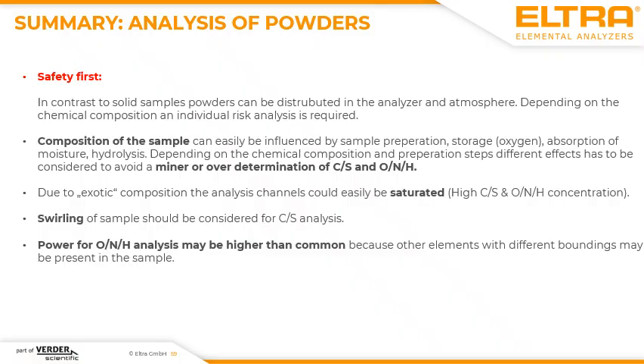And for ONH analysis, the most critical thing is the applied power. For example, when you are familiar with operating steel samples as solid samples, and now you are getting a steel powder, it could mean that you have to increase the applied power to make sure that all of the oxygen and nitrogen releases from the sample. These are the most important hints which I would like to give you when you are facing problems with analysis of powders.